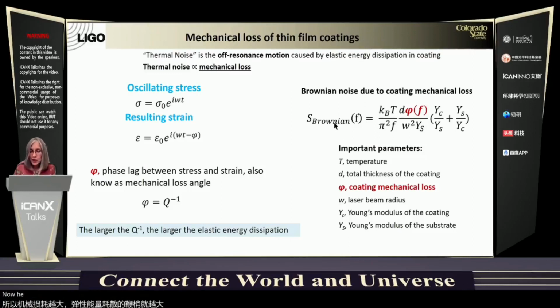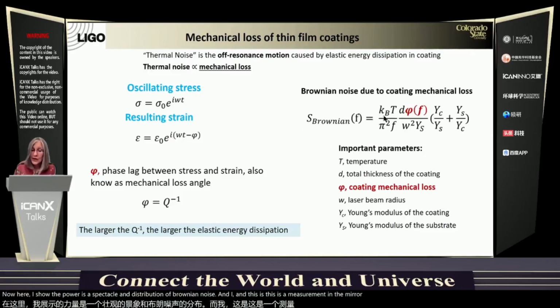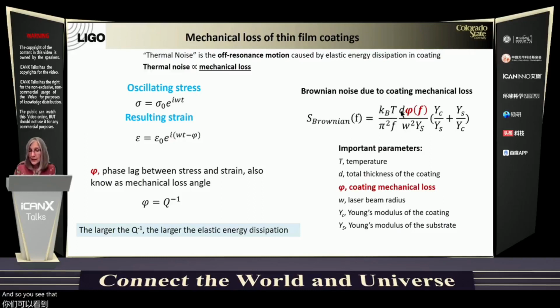Now here I show the power spectral distribution of Brownian noise, and this is a measurement in the mirror, and so you see that the Brownian noise of the mirror is proportional to the mechanical loss of the coating. It's also proportional to the total thickness, and has a dependence also on the Young modulus of the coatings.